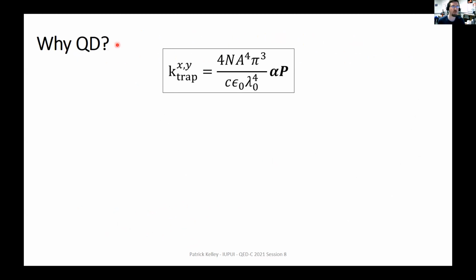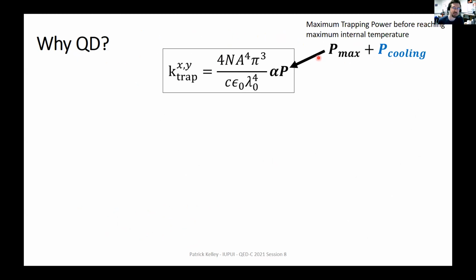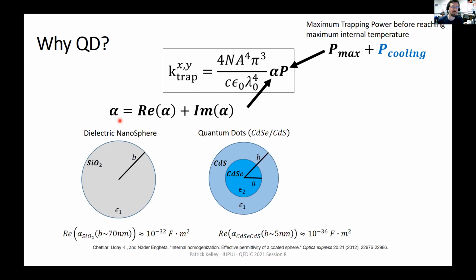So why particularly a quantum dot? And the interesting thing that a previous colleague of mine here at IUPUI did research on was that with a quantum dot, you have a cooling term that you can put to it. So the quantum dot, if you shine a certain light on it, will actually cool the internal temperature, meaning that you can increase the power of the laser that is trapping the particle. And that also has to do with the polarizability of the particle, where here's our quantum dot versus in most literature, you have a silicon dioxide or silica bead.